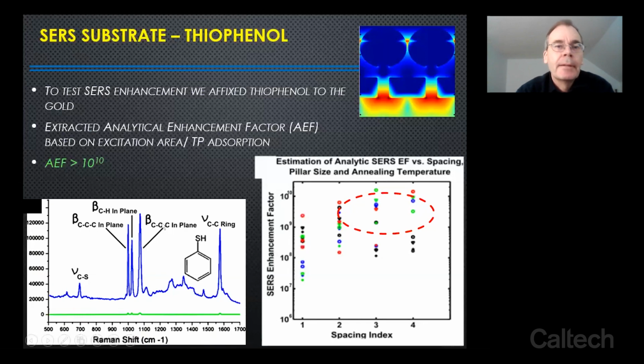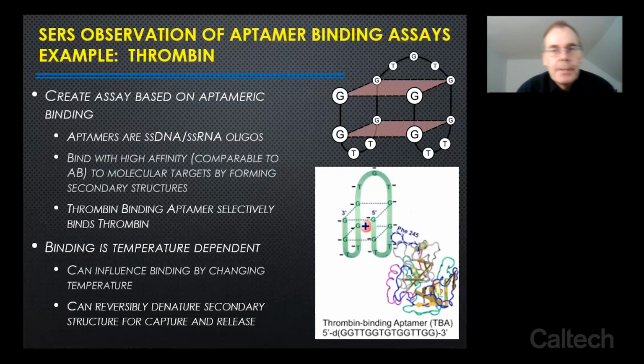So in this particular case, this spectrum shows you thiophenol that has been deposited on the edge of the nanobulbs. And again, we have this enhancement factor of 10 to the 10 times. And what we're trying to do is use this to measure things that are relevant that you cannot measure any other way. So for example, we know our blood contains thrombin. It's one of the coagulation factors. It's a very important part of the blood factor of the cardiovascular system. But the problem is if you want to measure thrombin and you take blood out to measure it, the thrombin immediately disappears because the blood coagulates. And so in order to measure thrombin, you really should be inside of the living organism.